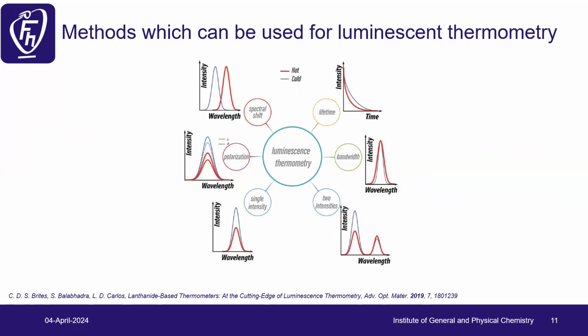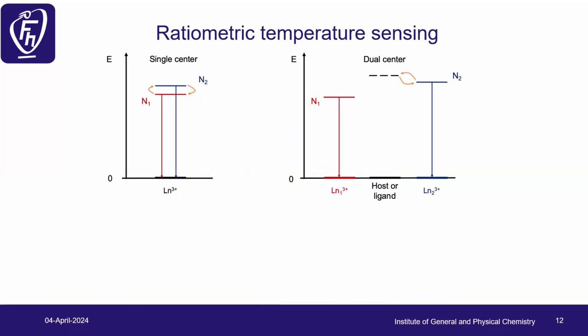Some are based on the spectrum shift, so the movement of the emission with temperature, lifetimes, then if we have polarization we can use polarization, bandwidth, so broadening, or the intensity of one level, a single intensity, or two. In the case of what I'm going to show, I work mostly on ratiometric temperature sensors, which are based on two different emitting levels.